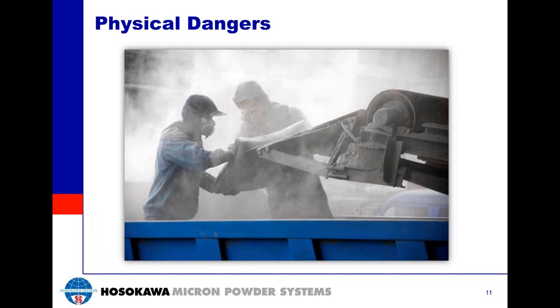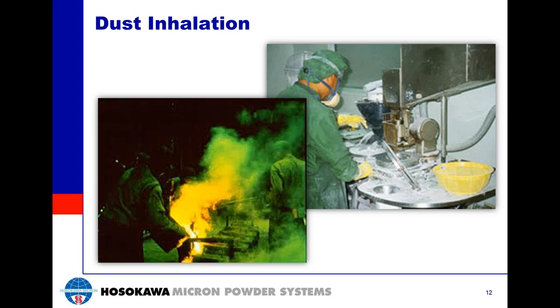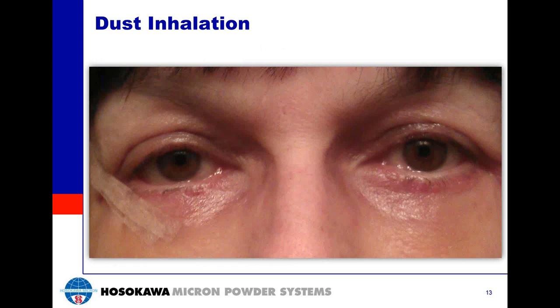Dust is a byproduct of many industries and can be a deadly material. For example, if you're an operator grinding a toxic material, your personal protective equipment includes a dust mask that filters 99% of particles 0.3 microns or larger. Without realizing it, you start to over-grind your material to 0.1 microns. Without analyzing your material, you have no knowledge of this over-grinding, and that dust mask is no longer protecting you. You're now inhaling toxic materials, which can cause long-term health issues and in some cases death.